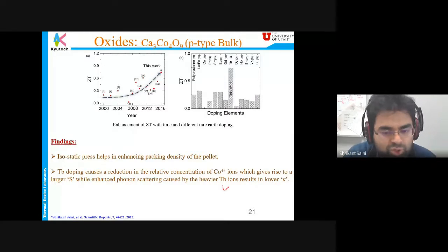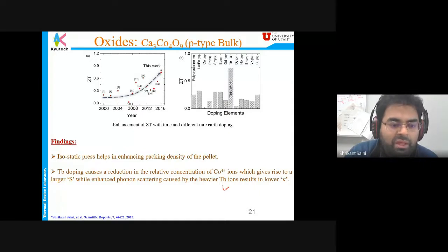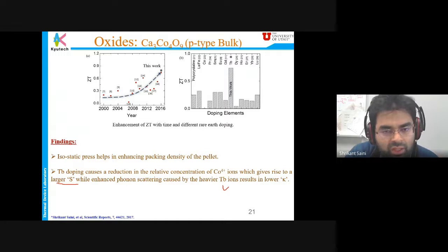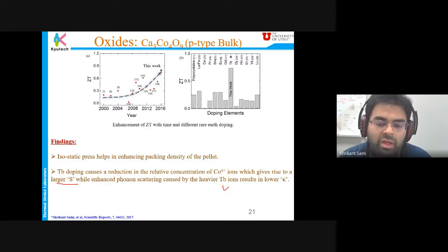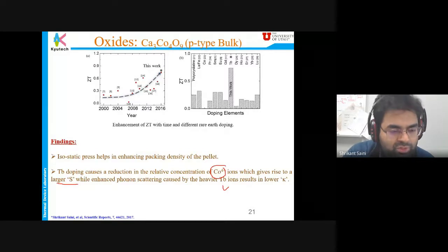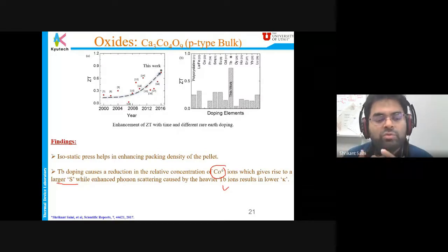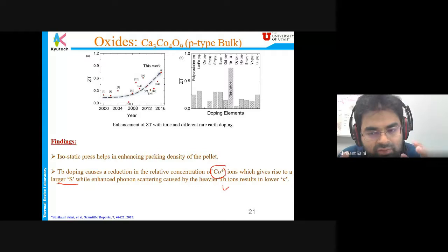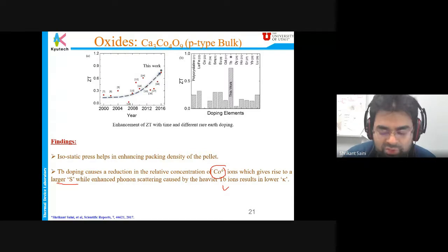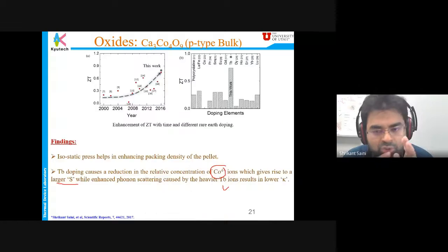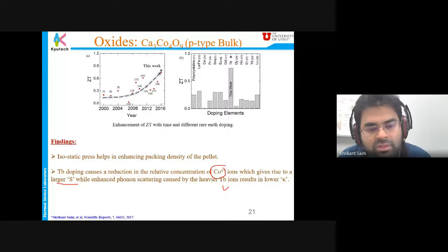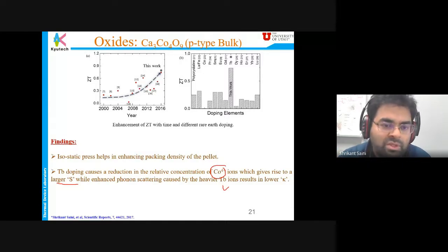Thermal conductivity drastically goes down, but at the same time the Seebeck coefficient increases, because the overall carrier concentration, which was governed by Co4+, reduces, which increases the Seebeck coefficient in this case. And at the same time, the electrical conductivity of this material increases because the grains are highly connected, with a melted-grains kind of structure, which I showed you in the previous slide. So all those three conditions which I showed you about ZT work very well here, and we have reported the enhanced ZT at this stage.